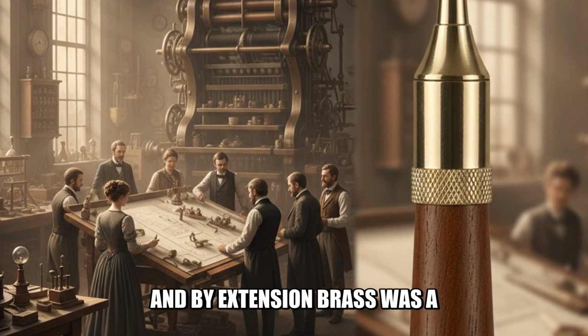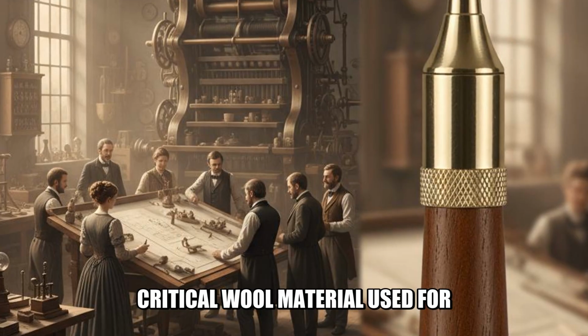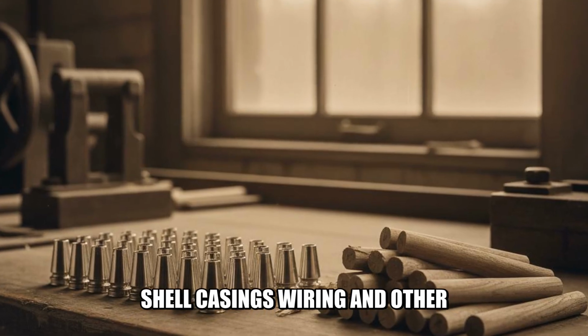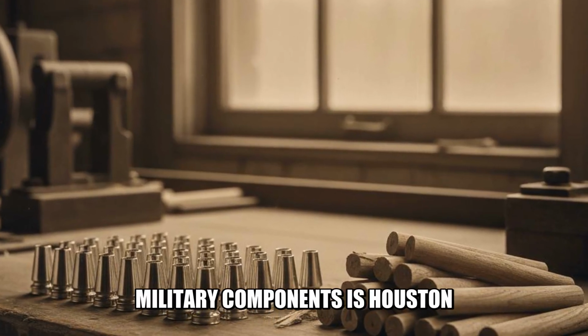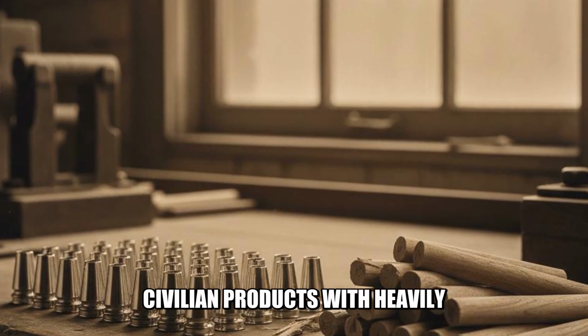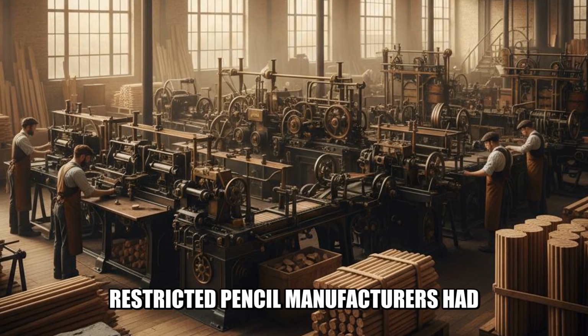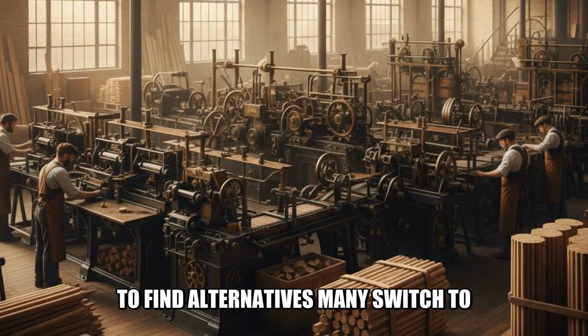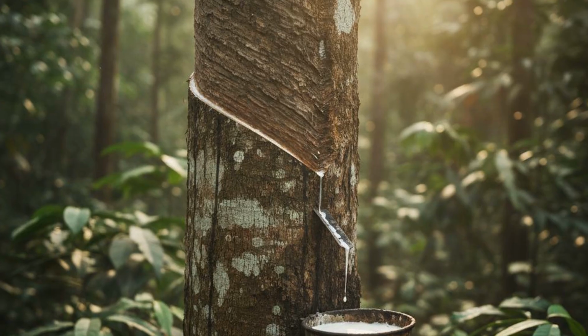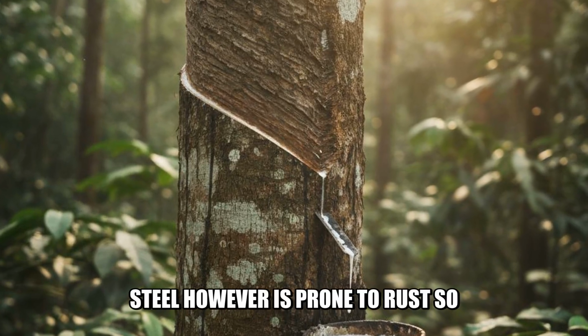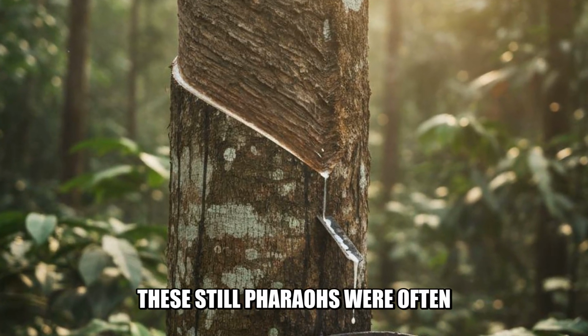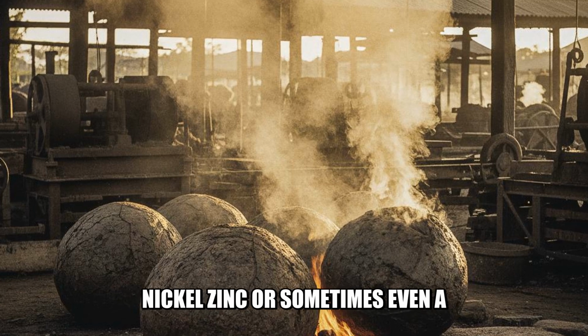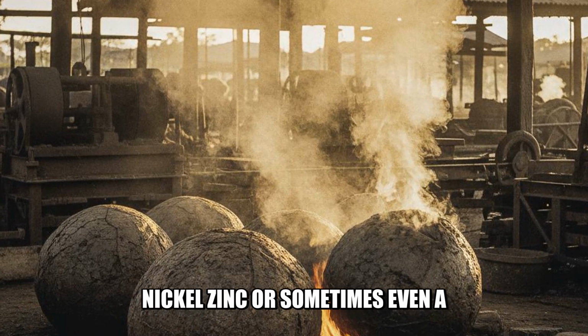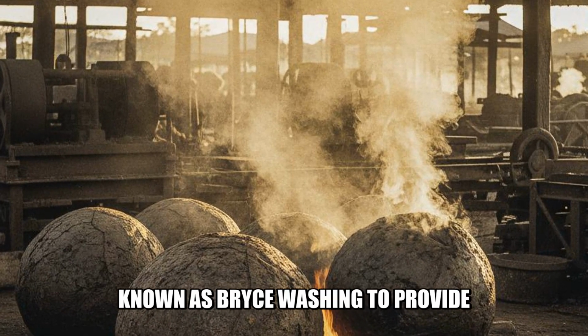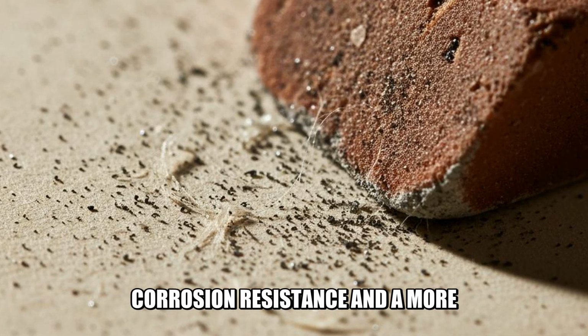The war also impacted the ferrule. Copper, and by extension brass, was a critical war material, used for shell casings, wiring, and other military components. Its use in civilian products was heavily restricted. Pencil manufacturers had to find alternatives. Many switched to using steel for their ferrules. Steel, however, is prone to rust, so these steel ferrules were often plated with another metal, such as nickel, zinc, or sometimes even a thin layer of brass, in a process known as brass washing, to provide corrosion resistance and